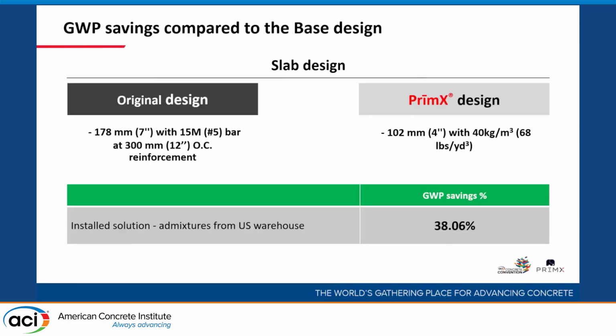And here's the comparison of what we were able to achieve on this slab. The original design, which was there before we arrived and offered to consider our technology, which was important for Amazon because they like to save CO2 on their projects, was a 178 millimeter, 7-inch thick slab with number 5 rebar reinforcement at 300 millimeter, or 12 inch, spacing. And we were able to cut it down to 4 inches, and the dosage of the steel fibers was 68 pounds per cubic yard. You can see where a lot of the savings come from, of course also from replacing the steel, but we had a verified GWP savings of 38% on this project. Most projects are around there, some are 50%, some even more.